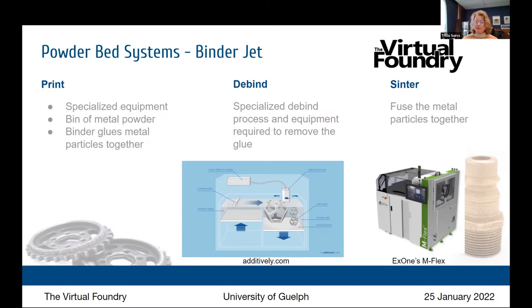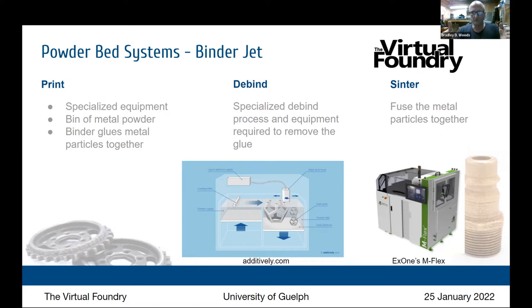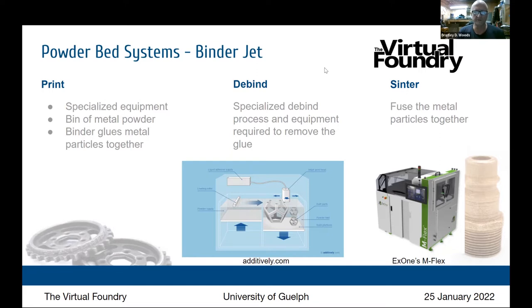The binder jet glue is laid down just like an inkjet printer. They print into a cubicle that they completely fill and seal — a solid block of powder — then put it in an oven for two or three days until the glue dries. As a secondary step called depowdering, they carefully remove the part from the loose powder. The parts that were glued together stay as a solid object while the unglued powder falls away. At this point the part is very fragile — they call it 'green' — and there tend to be a lot of losses during this process.